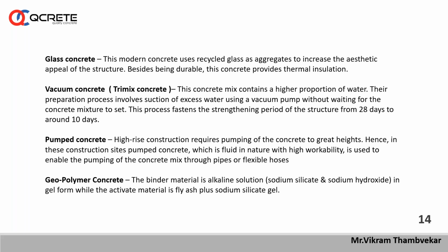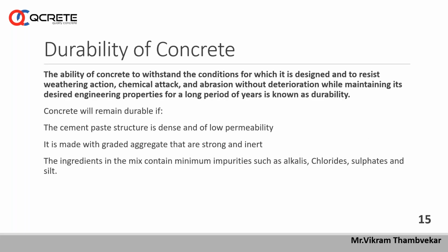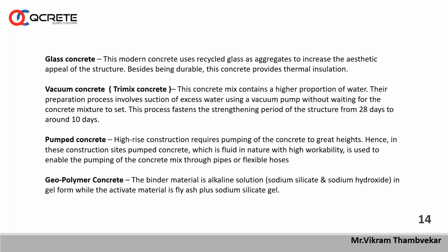So either you have to cover it with gunny bags with water immersion, or with water, or better to use such RMC or concrete when there is a very low ambient temperature. Low means up to 30 degrees or 32 degrees. In very hot ambient temperature, try to avoid the pumping of concrete. Then further, geopolymer concrete is of course in R&D stage. Now we can use it for purposes other than structural use.